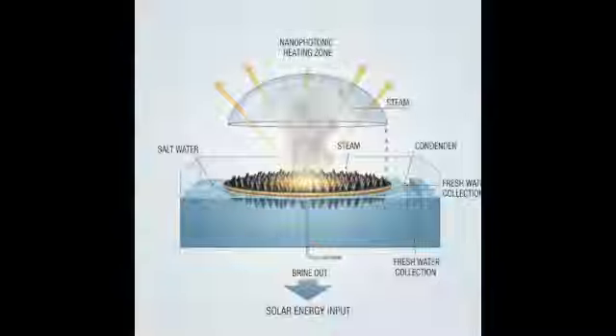Why carbon? What makes it so good for this? Its electronic structure. Carbon materials, especially graphitic ones, have loosely bound electrons, pi electrons, that can absorb light across a very broad spectrum from UV through visible and well into the near infrared, which contains a lot of solar energy. Broadband absorption. Plus, they're generally stable and relatively low cost, right? Especially carbon black. Generally, yes. They convert that absorbed light into heat very effectively. Adding them to membranes like CNTs has shown flux enhancements of 12–40%. Simple spray coating of carbon black NPs onto PVDF reportedly raised the surface temp by almost 14 degrees C in under 3 minutes under standard sunlight.